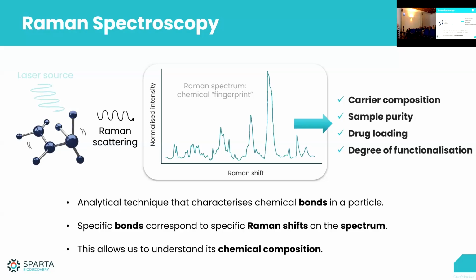We use a near-infrared laser specifically because it doesn't damage the particles. You could use a green laser, which would give more signal, but it would also damage the particles at the same time, and we don't want that. As well as that, there's quite a lot of natural fluorescence in biological particles, especially when we're looking at cells or exosomes, which would interfere with the Raman effect.